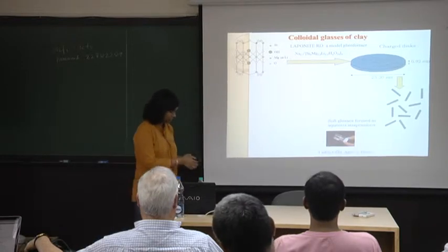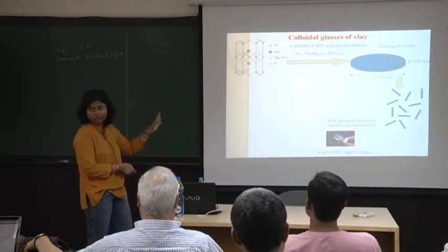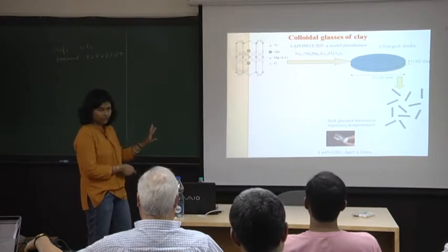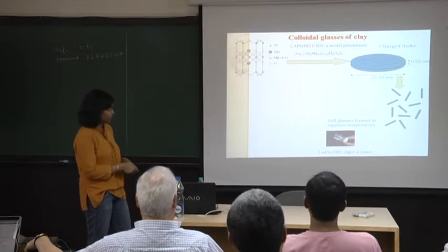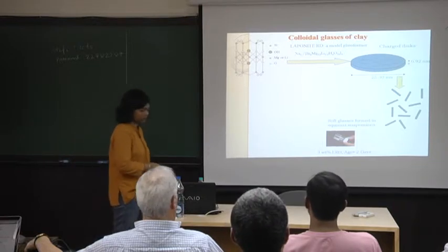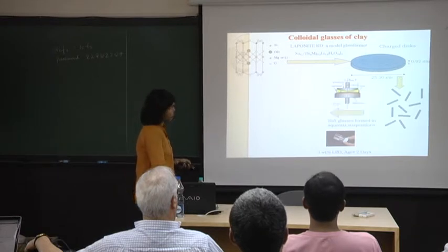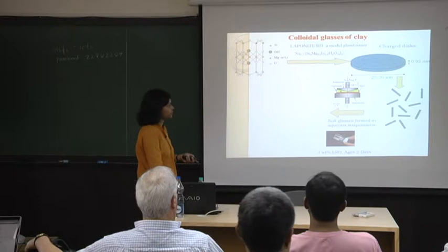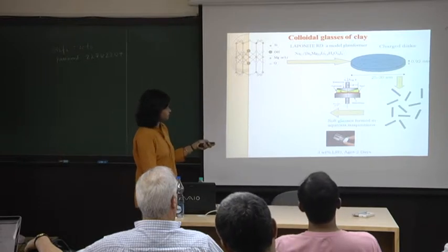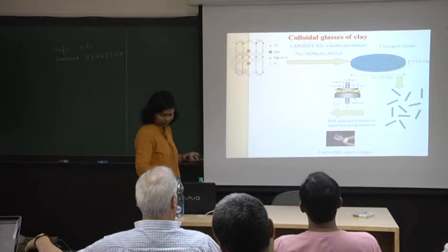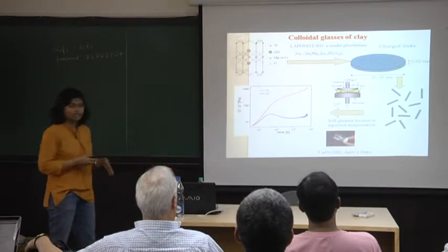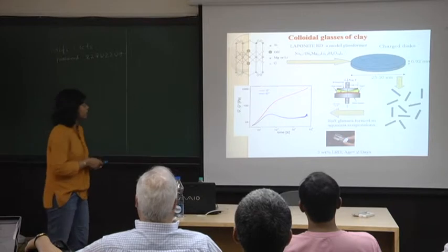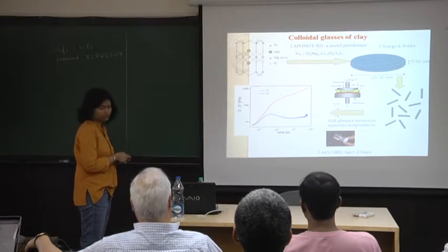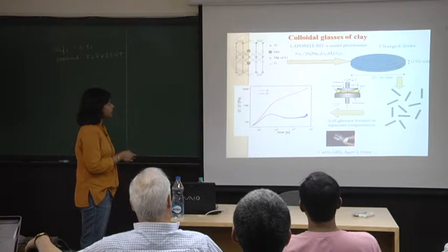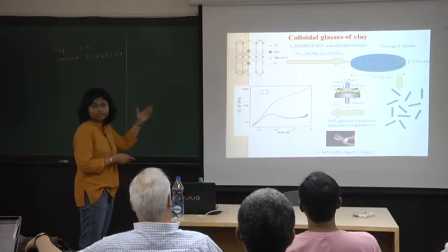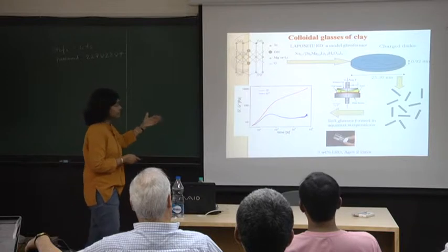This is basically a 3 weight percent suspension, which is a volume fraction of about 0.15. You take a Laponite suspension, wait for 2 days, and you see a solid-like material here. It shows signatures of soft glassy rheology. This is a rheometer geometry. Using very, very small strains, if you measure the elastic modulus G' and the viscous modulus G'', you find that the elastic modulus evolves a lot, and this is a spontaneous evolution.